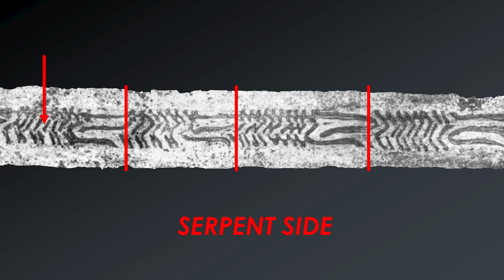Here you can see that about 5 to 10% was ground off. And here you can see that the grinding went to about 25 to 30% deep. You can also see that the rods alternate in their twisting direction, with the 2 outer rods going in one direction and the central rod in another.